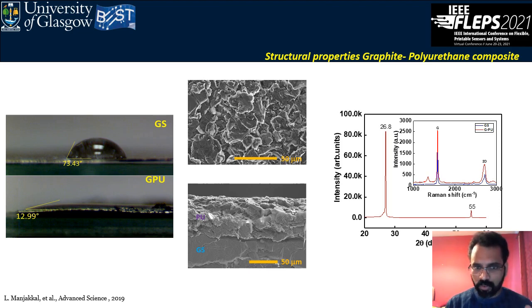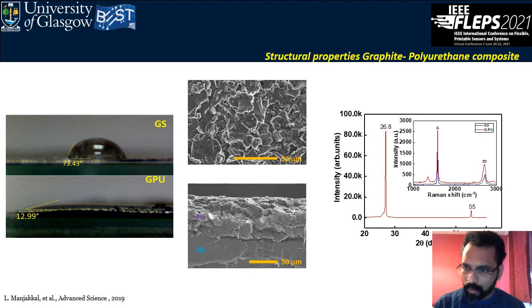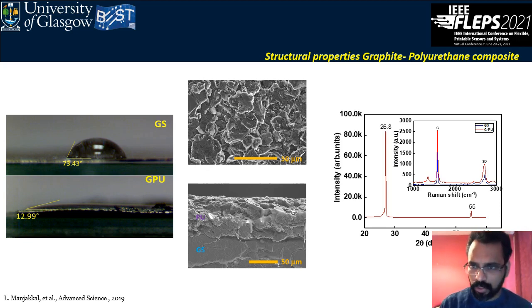And here you can see the cross section of the graphene sheet and polyurethane composite. We further studied the crystalline properties of the material through XRD and Raman spectroscopic analysis. You can see here that in XRD the peak is more towards the carbon graphene sheet, and it is more similar to the carbon. And in Raman spectroscopy, mainly the G and 2D bands are more related to graphene, and peaks are observed. A small peak here we observed is due to the structural defect of the composite material.